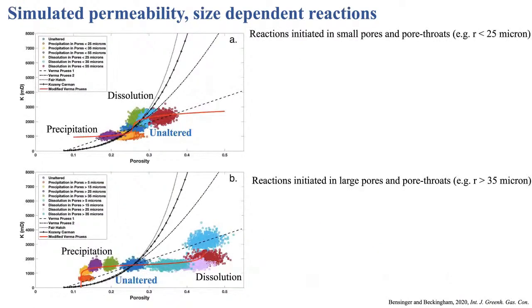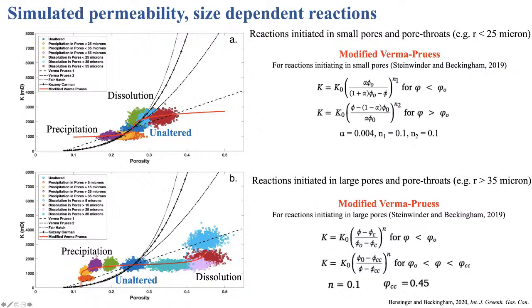Now, if we consider a scenario where reactions initiate in small pores and pore throats, on the top, you have initial rapid changes in permeability and don't start seeing changes in porosity until you're impacting larger pores and pore throats. On the bottom, if the reactions initiate in the largest pores and pore throats first, you will see large changes in porosity with little change in permeability, and then start impacting permeability once reactions are impacting smaller pores and pore throats. And neither of these is captured by these macroscopic porosity permeability equations. But in red here, we have modified the Verma-Pruess equation, and we're able to find something that is a better reflection of the porosity permeability evolution for these systems.